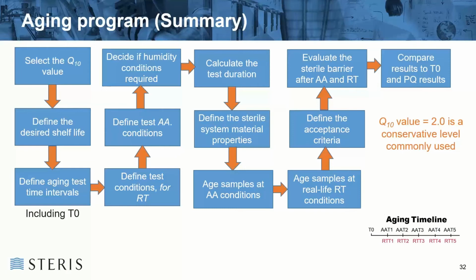Define the test conditions, say for real-time aging. Is it going to be 23? Is it going to be 30? Is it going to be 20 degrees? And what humidity levels you're going to include in there. Again, it needs to be realistic in that. Define your accelerated aging conditions, what they're going to be, and what temperatures that's going to be. Is it 50? Is it 55? Is it 35? Whatever the case may be. And decide if humidity conditions are going to be required and what levels. Then calculate your test duration for your accelerated aging, and define the sterile barrier system properties.